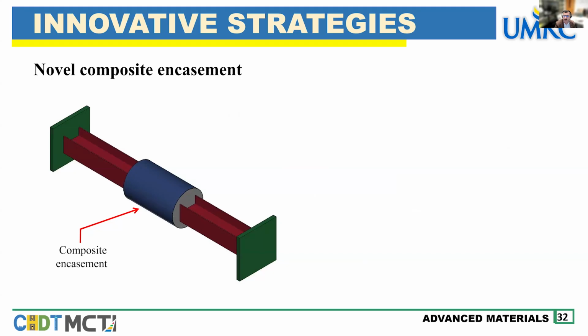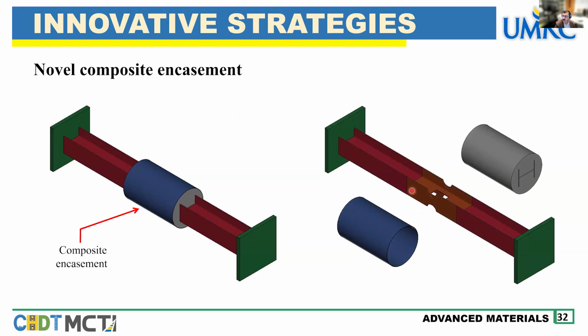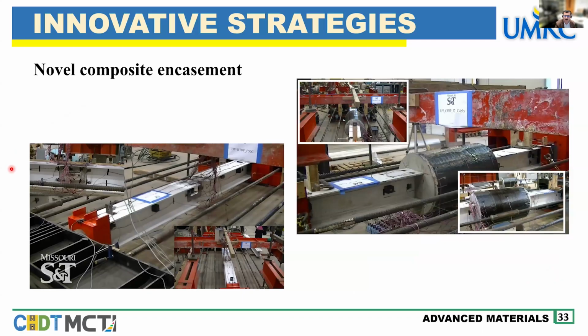So this is the H pile here, and we simulated the corrosion, as you can see here, by milling. And this is the proposed composite encasement, which includes the CFRP jacket and also the concrete fill surrounding the corroded region here. As you can see, this is a kind of band-aid for the corroded, damaged steel H pile. And we tested, this is also a huge matrix. We tested several steel H piles with different corrosion severity here.